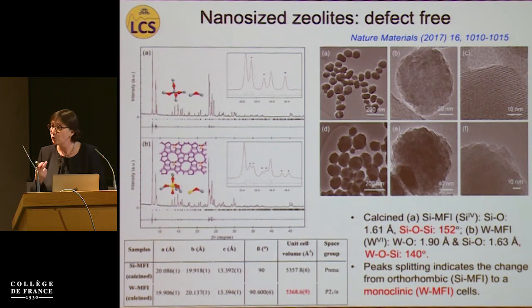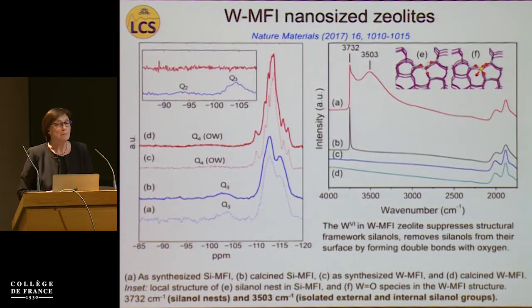This has been observed before once aluminium was introduced in MFI type zeolite. But in order to prove that our materials do not have any defects, we also performed silicon NMR spectroscopy, and here in red you could see only the Q4 species which are measured for tungsten-containing zeolite. From the CP MAS, you could see a flat line confirming that there are no silanols in the tungsten-containing zeolites. While in the pure siliceous form, we could see an abundant amount of Q3 and Q2.